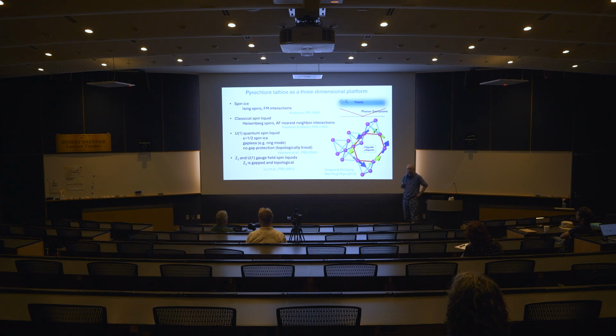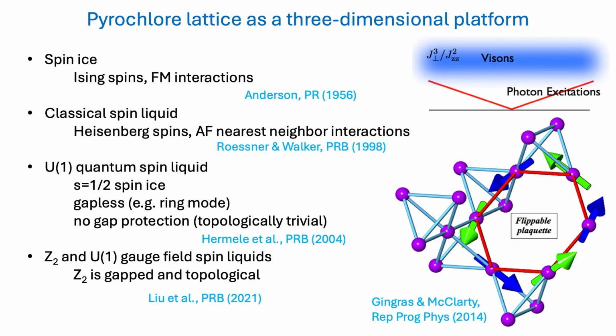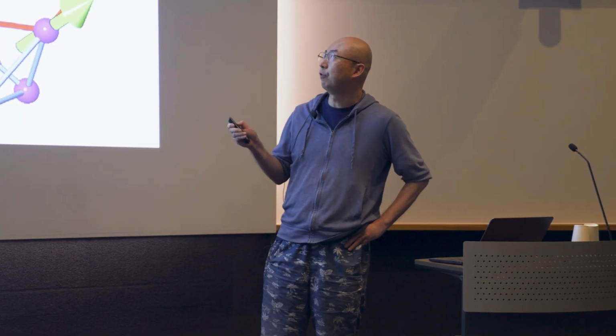It turned out that this is actually a relatively trivial case, because if you look at the S equal to 1/2 spin ice, basically you have these spins all pointing to the middle or away from the middle of the tetrahedron. If you have 6 spins aligned like this in a head-to-tail ring, imagine at one moment you suddenly flip all of them to the opposite direction. Then you still have, at the local site, one in, one out, just opposite. Overall, the energy of this system should not change. So basically, this is a zero energy mode, which allows you to flip the whole 6 spins all together instantaneously.